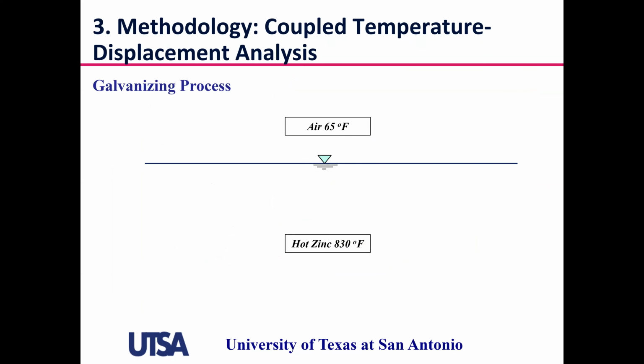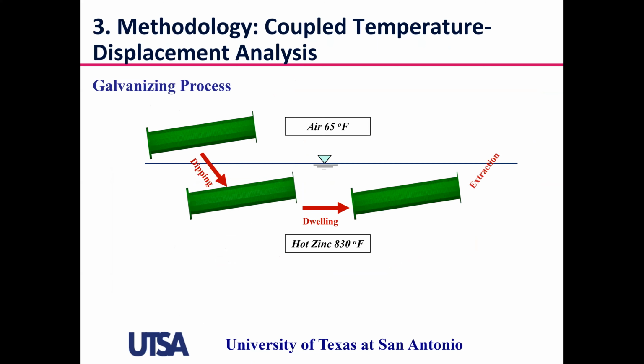So a typical galvanizing process consists of 4 steps. So first, you dip your pole, typically at an angle, and then you leave it there for some time to make sure the zinc attaches to the pole and the base. Then you extract it, and then you finally let it cool down. So this is the process that we are modeling through our finite element simulation, and for that we do it through a coupled temperature-displacement analysis because we are interested in both the temperatures and also the mechanical response of the structure.